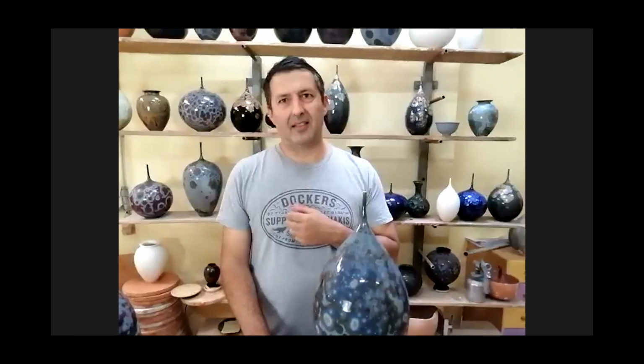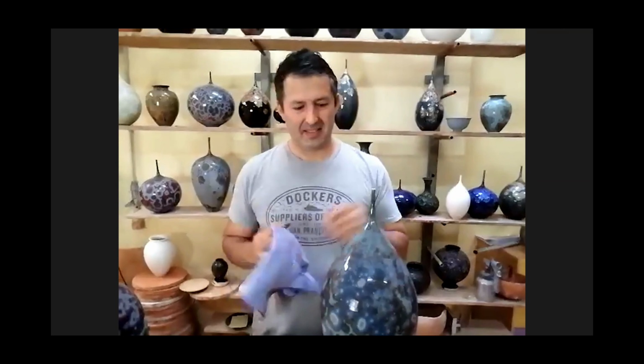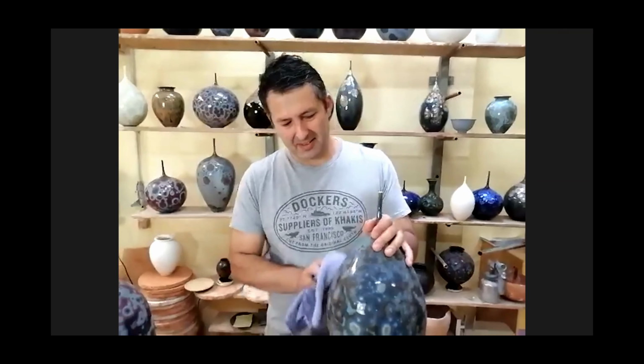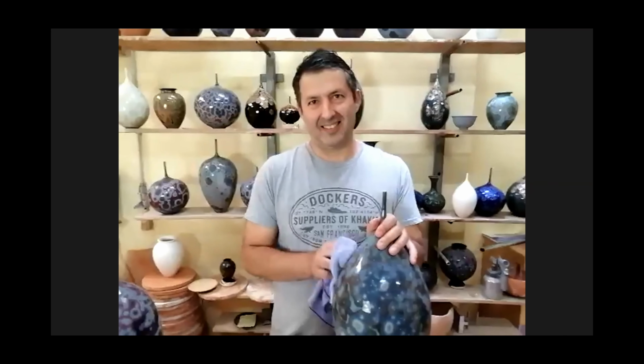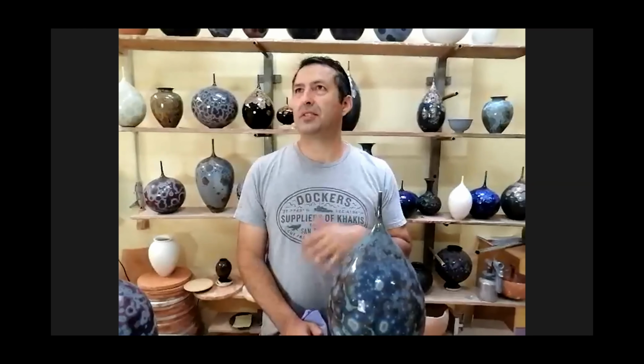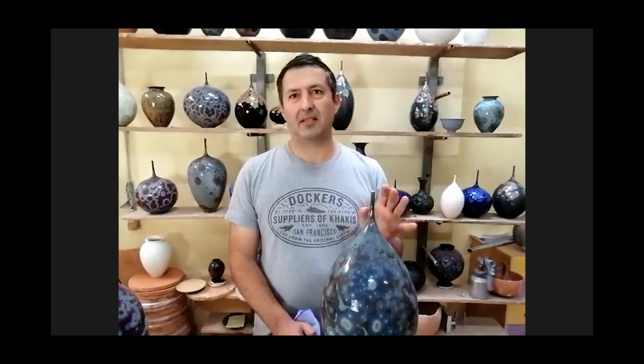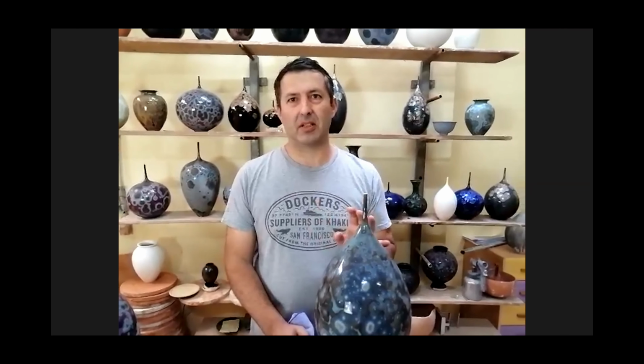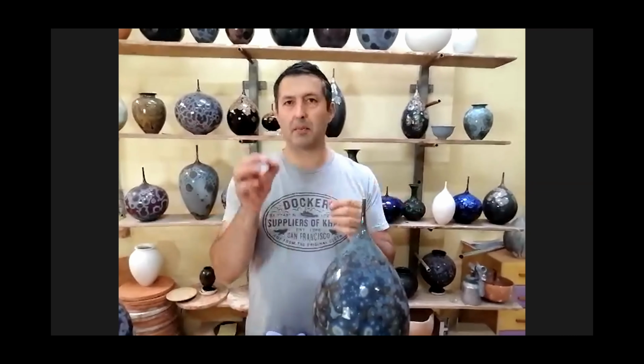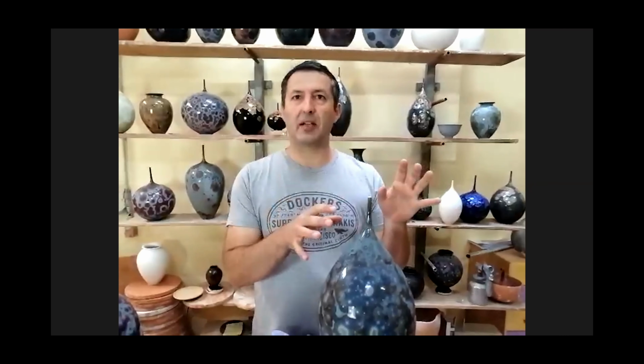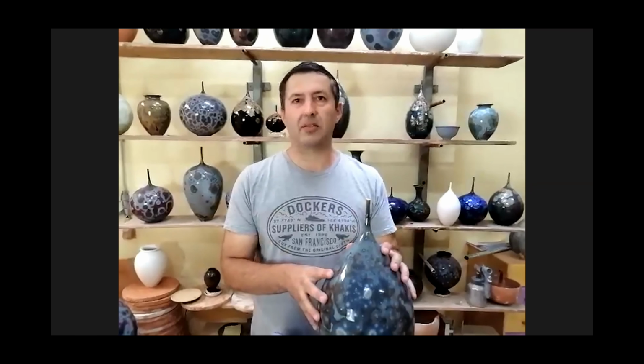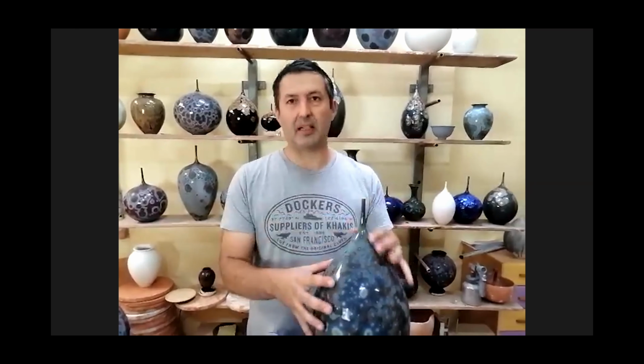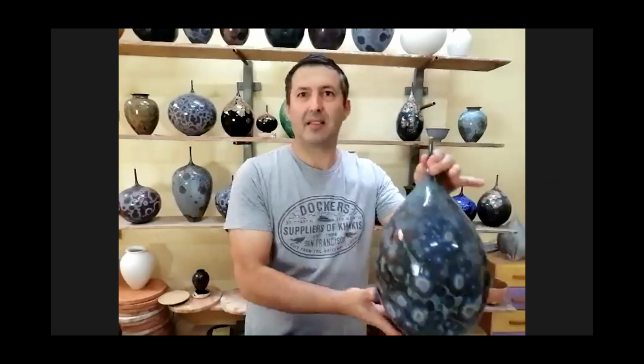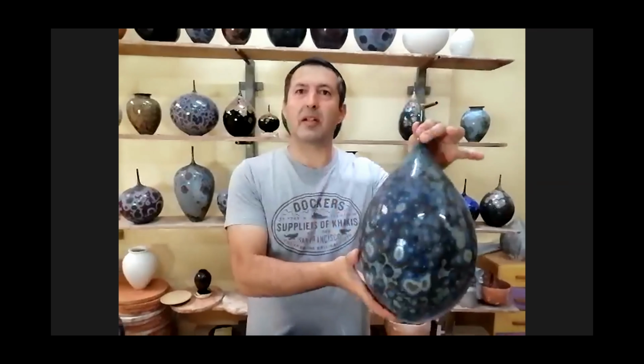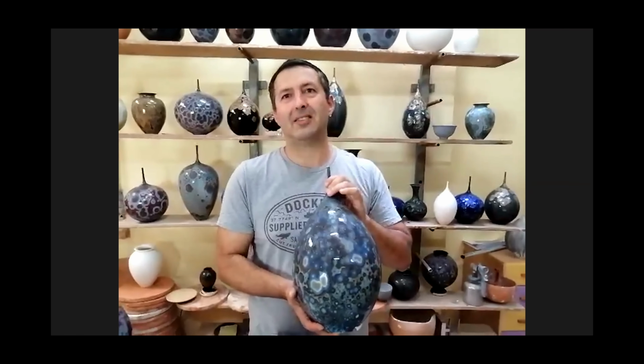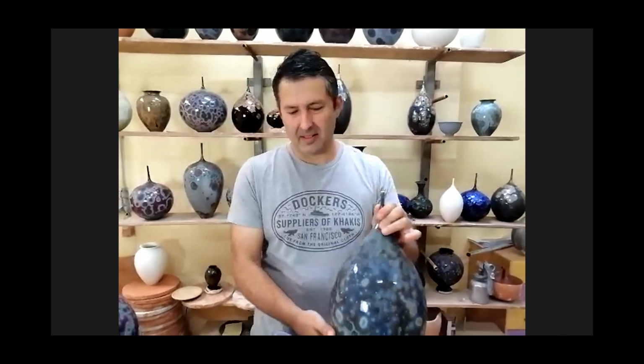Now this piece has less than 1%. We don't know exactly the amount, but our experience says now there is more or less 1% of copper. What happens if you use 6 or 7% of copper? It will be black, absolutely black. Not nice. If you have one recipe and you use 1% of copper and you do post-reduction firing, it's beautiful. If you use 5%, it doesn't work. But if you use 5% and you put the pot in acid, after acid you clean and you do the post-reduction firing, it works. Okay, understand?